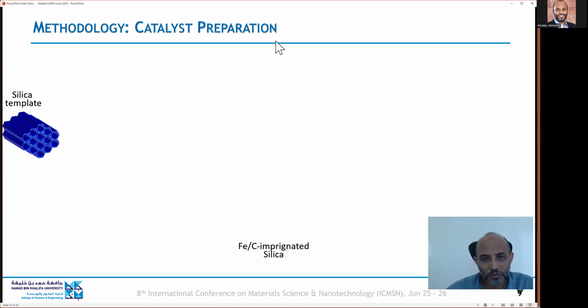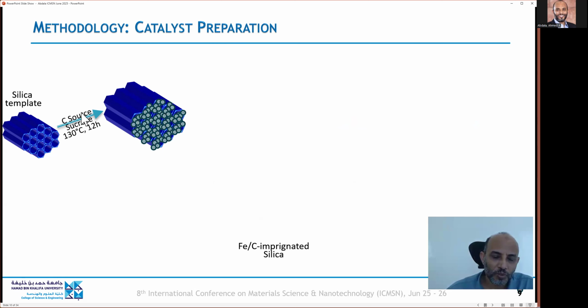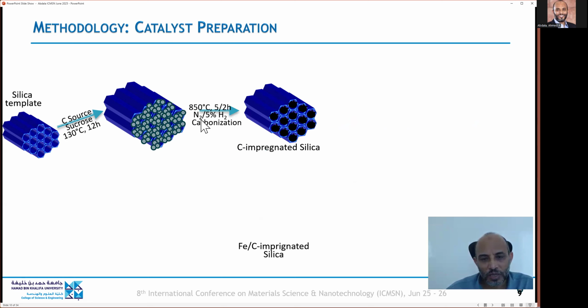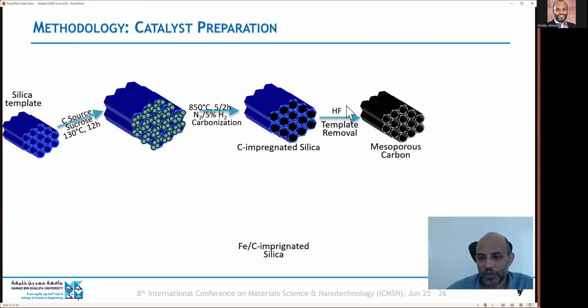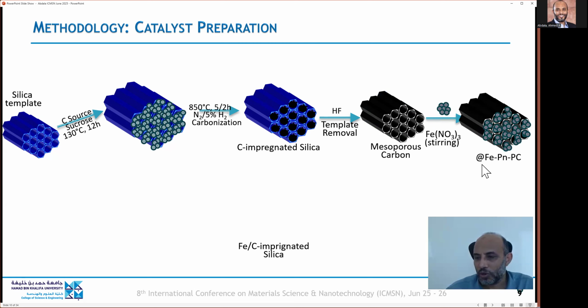The next step is to prepare the catalyst using this templated silica. So we adopted two different approaches. In the first one, we do a two-step process. The first step is to prepare the mesocarbon material, and we use sucrose as a carbon source. We impregnate it into the silica template, and then we carbonize at 850. So now we have mesocarbon impregnated into the silica template, and then we can etch the silica template using hydrofluoric acid to end up with the mesoporous carbon, and then we can impregnate the mesoporous carbon with an iron precursor, and then we can hydrothermally reduce it to iron nanoparticles supported in porous carbon. So this we call a post-confinement technique.